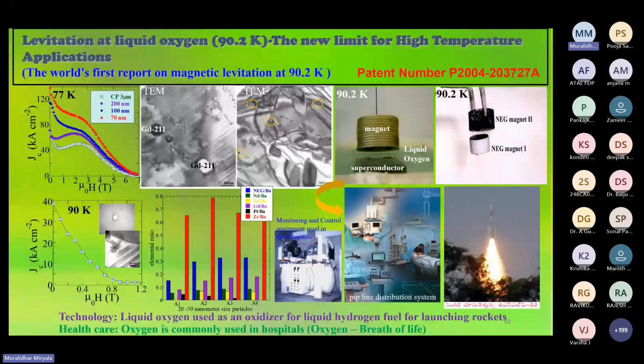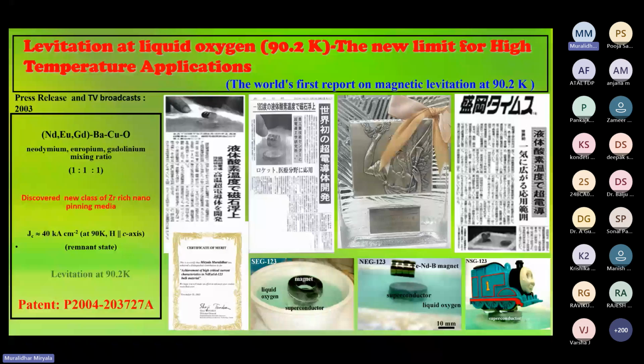As a result, the critical current density, Jc, I showed at 90 Kelvin. The bottom picture is 40 kiloamps per centimeter squared. It is quite enough to levitate a magnet. In the case of YBCO, it was 77 Kelvin that we showed, but here it is 90 Kelvin, the first report. This is fundamental, and it can be used for non-contact liquid oxygen pumps in hospitals, and also rocket launching technology for superconducting bearings. Again, these results appeared in the news and TV, corresponded to the patent, and also won awards from Japan and different countries.